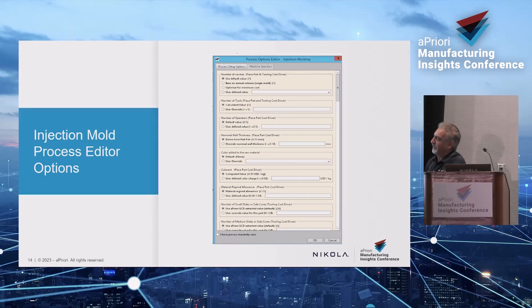It's just a checklist you go through. Colorant: if it's a molded-color part, you add colorant — usually about $1 per kilogram for a molding color like black. Then there's re-grind: how much re-grind will you allow in one part? That's a huge cost saving — the default is 25%, which is pretty much the industry standard. If it's not a Class A part you can go higher. The gates and runners get re-ground and reused. After you go through this cost modeling checklist three times, it comes naturally.